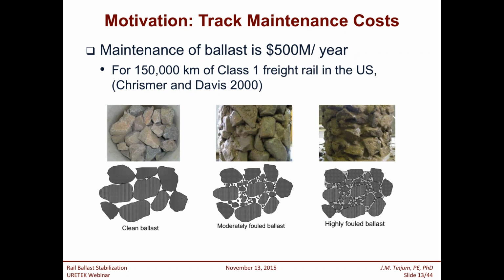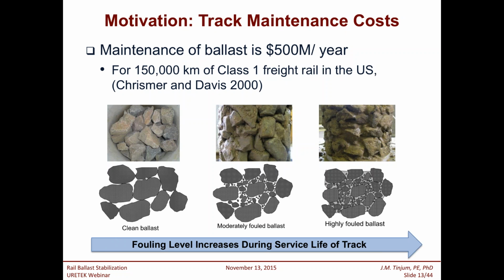What happens over the life cycle of a ballast section is we start with clean, controlled, engineered ballast. It generally starts to accumulate smaller fine particles, either from degradation of the particles themselves and or intrusion from environmental conditions outside, such as wind-blown silt, spillage from the cars themselves, or pumping of fine-grained material up from the subgrade. So at some point, you're going to get heavily fouled ballast, where the void structure is completely filled with the finer materials and moisture, and the strength of the fines controls the strength of the ballast, not the larger particles themselves. So as this fouling level increases, the service life of the track deteriorates and decreases.